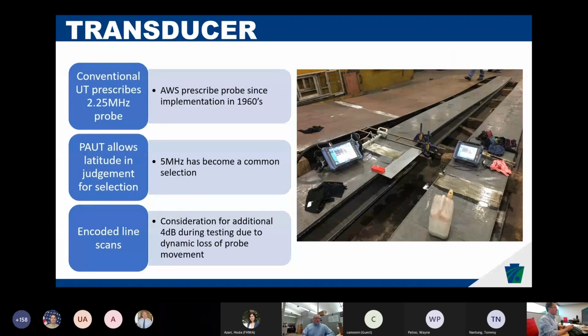So the transducers, slightly different approach than the currently prescribed AWS method that uses a 2.25 megahertz probe, and that's been there since the 1960s. It's there for a number of reasons, right? The 2.25 allows a good penetrating energy. It allows a good wavelength for detecting certain size flaws. It allows you to easily account for some of the attenuation parameters.